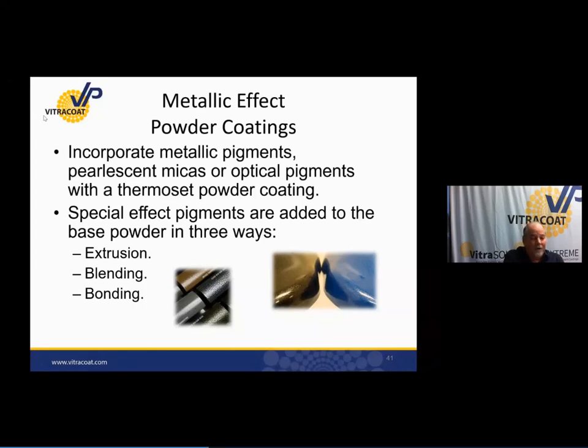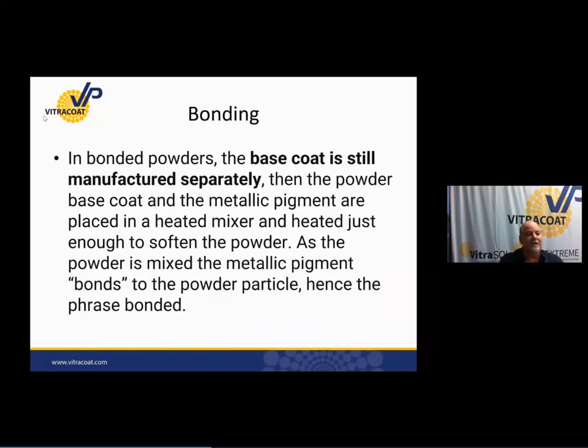If I have powder and I dry blend this heavy stainless steel metallic in it, they're going to fluidize differently. They're going to take on a charge differently. They're going to spray differently, and thus they can give me a different look. The application window is fairly narrow. The bonded idea is that we take the base coat, just like we would in a dry blend. We do manufacture it separately, and then the powder base coat and the metallic pigment are placed in a heated mixer that just softens the powder enough for the metallic to adhere or bond to the material itself.